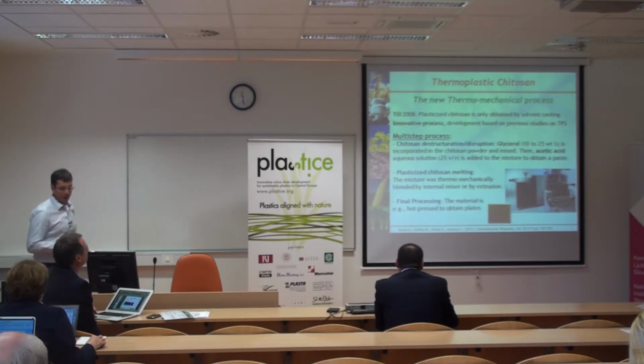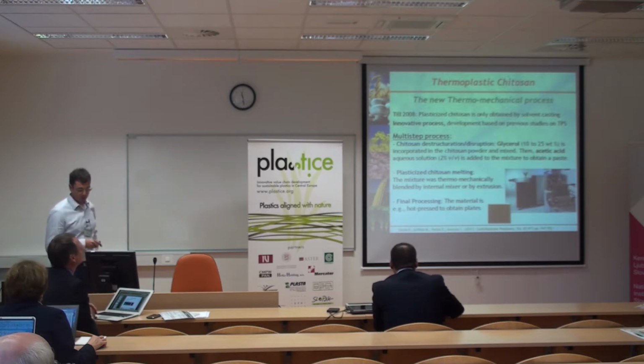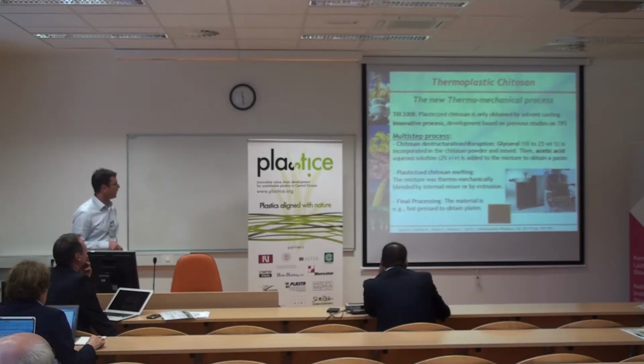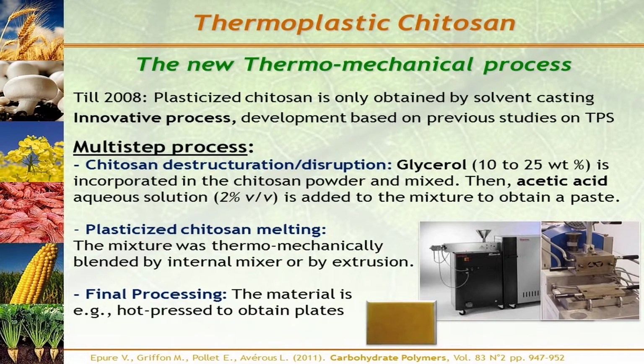So it's a multi-step process, and in the first step we have the destructuration of the chitosan, and for that we prepare, as previously shown, a dry blend using glycerol with the chitosan, and then to this dry blend we add an acetic acid aqueous solution. So we obtain a kind of paste that we feed to an extruder or to an internal mixer like we have here. And then this is thermomechanically blended, and at the end we obtain thermoplastic chitosan material, which can be processed again, for instance, to obtain plates for material characterization.